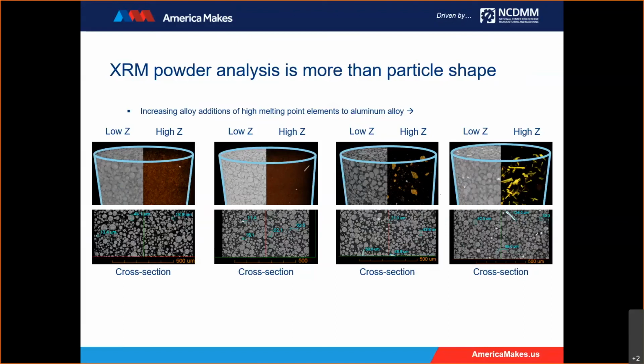On the leftmost image, we have a small high density particle. And in the image to the right of that, we can see 1 particle in a needle. But you can see that as we increase the alloying elements, it forms these globules and then really large needle structures. And this was an issue where the supplier did not mix the alloying elements sufficiently before atomization, and it showed up as brittle fractures in the tensile specimen.